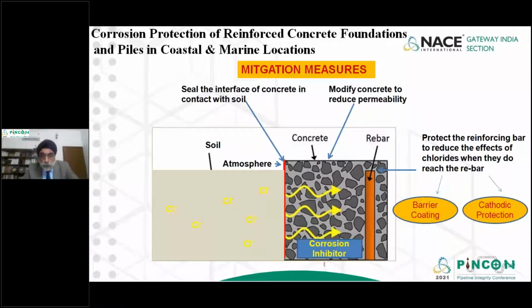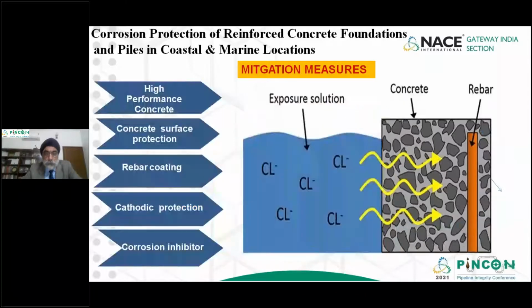Another strategy is to put in corrosion inhibitors, which would not allow corrosion to occur on the rebar and will keep the rebar in the passive state. We can also put in some chemicals within the concrete, which would reduce the permeability of the concrete. That means it would not easily allow chloride or sulfate ions to move from the soil into the concrete and hit the rebar. So these are various strategies which can be adopted to prevent corrosion of rebar.